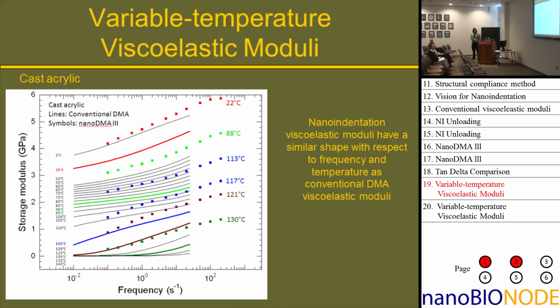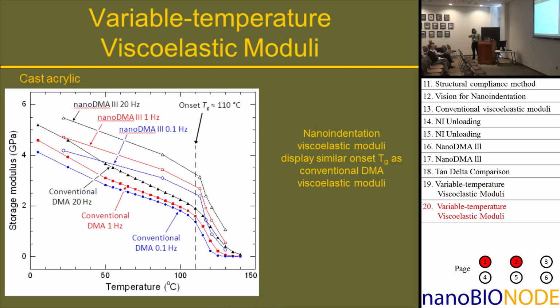So now if we go to another parameter space where we start to vary the temperature, as we do conventionally. So these solid lines here are conventional single cantilever DMA measurements, and the points here are the nano DMA measurements. And again, we find that it's always systematically higher, but the shapes are similar. So for instance, you can see this green curve here is concave up. This blue curve here is concave down, which is similar. And again, you could also plot this data as a function of temperature. And you can see that the onset Tg lines up pretty well between the nanoindentation as well as the